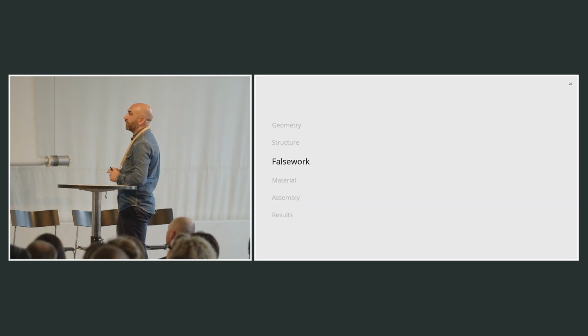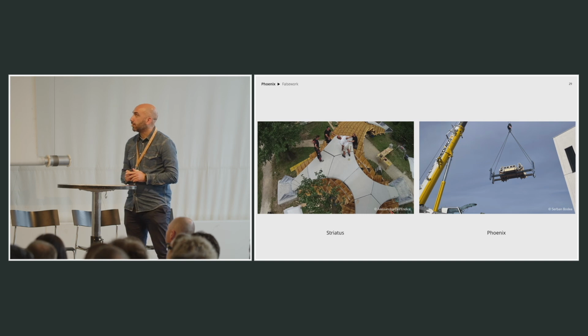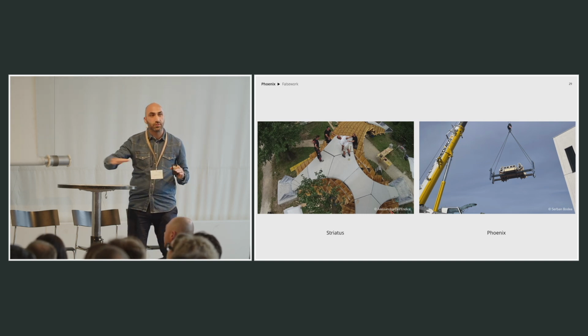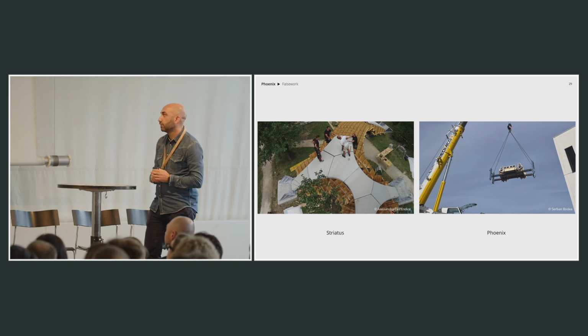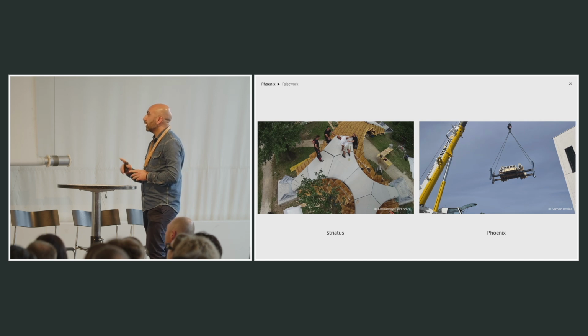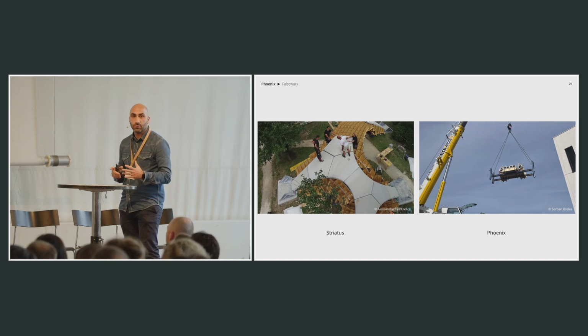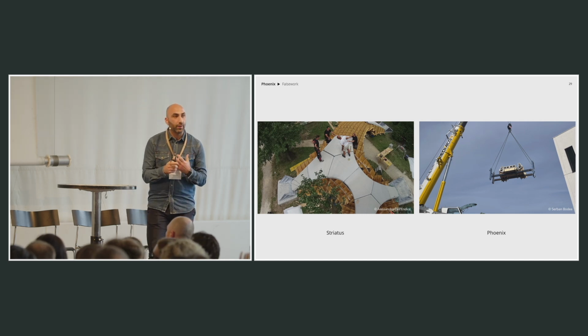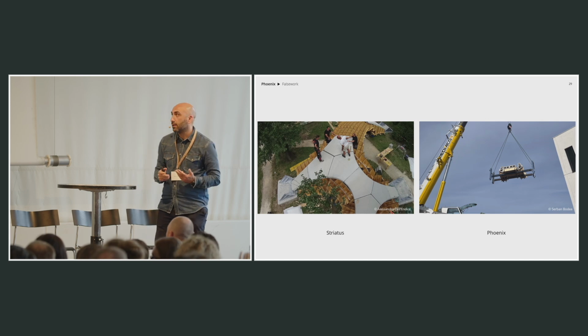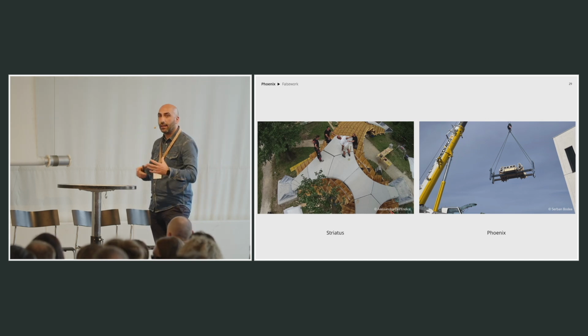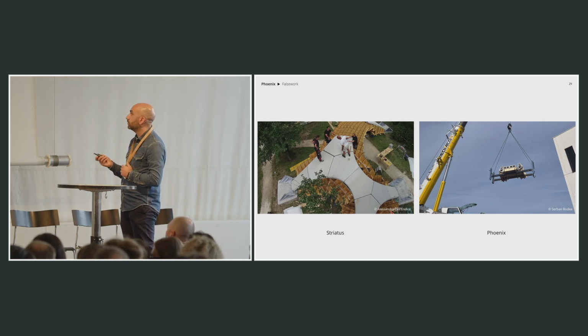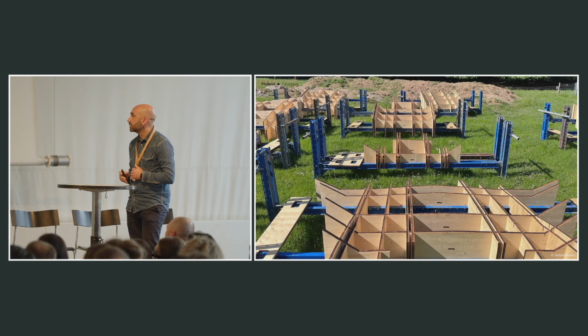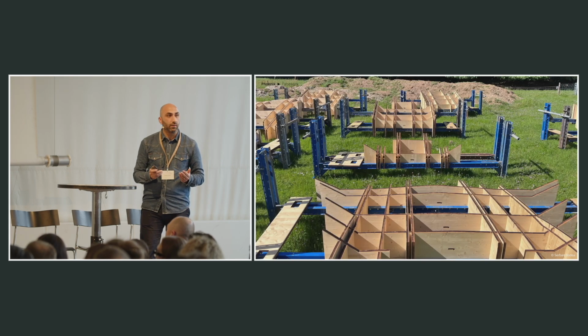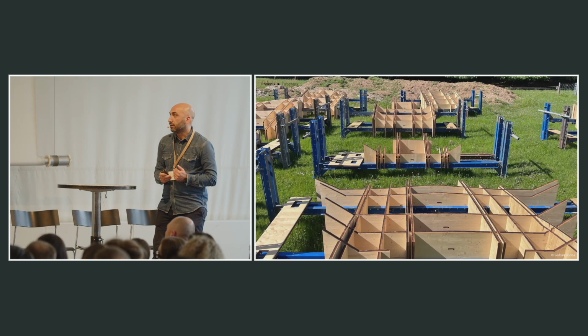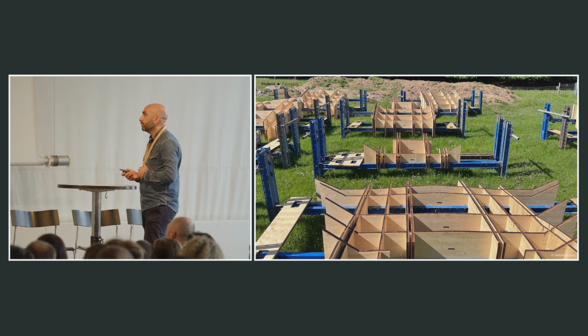On the false work, we went from this continuous timber waffle with a lot of wood that we built in Venice to a different system with cassettes, which were integrated with commercially available Doka elements, so these blue beams that you see around the components. So we could reduce by 50% the use of wood per square meter.